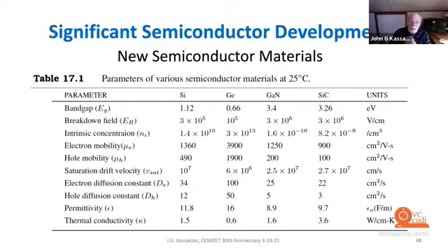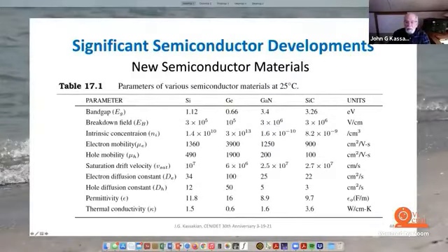So what else is happening with semiconductors? Well, here's a materials chart of materials that are used for power semiconductor devices. Of course, we all know silicon, germanium, and now we have gallium nitride and silicon carbide, which are the wide bandgap materials. And these have a bandgap that is about 3 times silicon. Forget germanium, we don't use germanium anymore. But relative to silicon, gallium nitride and silicon carbide each have about 3 times the bandgap, which means that their intrinsic concentration is very low. So leakage currents at junctions are extremely low. The devices can operate at much higher temperatures.